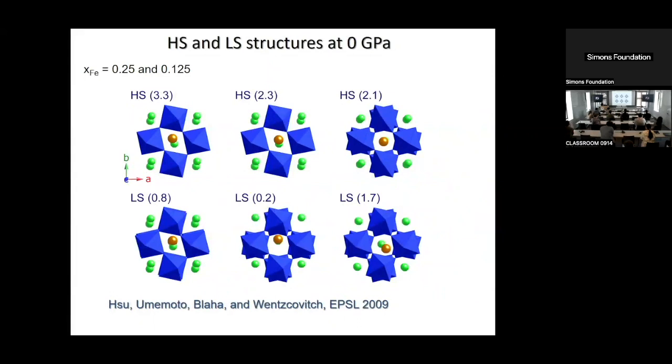If you're studying Mars, it's different. Lower iron at low pressures, even the high pressure form of iron, HCP iron, you can't reproduce. I haven't seen a functional that reproduces the equation of state at low pressures. Above 100 GPa, PBE gets it right. But below, you have antiferromagnetic, I think, fluctuations in HCP iron. That's what I read. I don't understand that, but not to mention, if there is magnetism, you have magnons. We have not introduced magnons in this calculation, but that's iron.